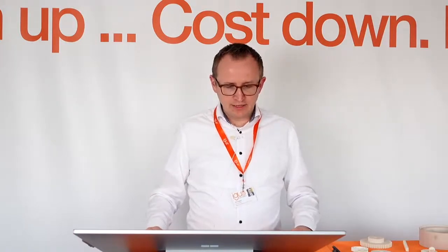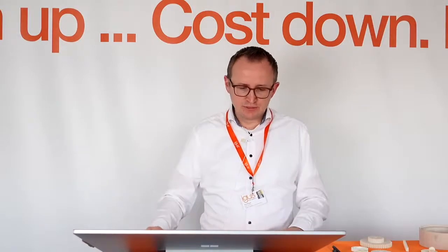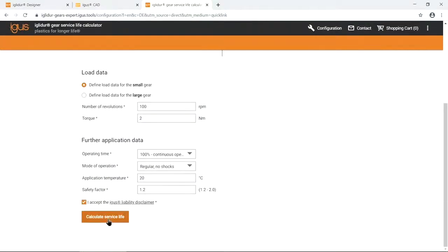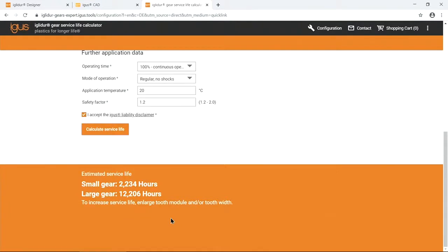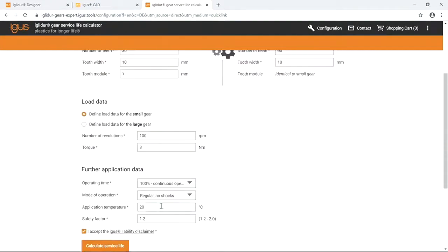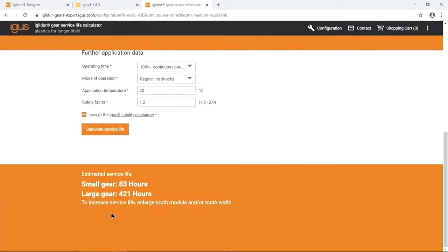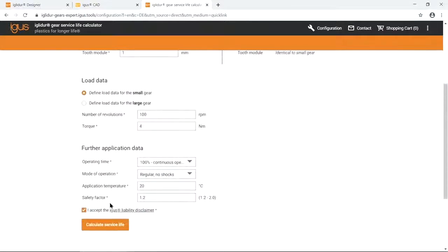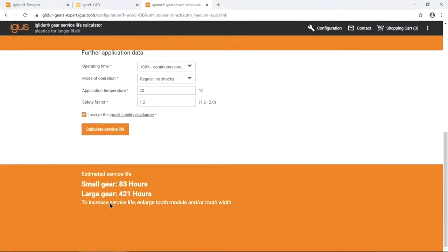But let's say we now have a stronger application. I'm increasing the torque from 1 to 2 Newton meters, and no change so far. I'm explaining later why. Okay, so at 3 Newton meters, we see already a big change here. The lifetime is a lot reduced, and if I'm increasing to 4 Newton meters, you see it's a really low lifetime in hours in this case. And yeah, let's say you have such a case, then it's not done by saying, okay, it's not working, I can look into something else, because now it's the point where you can play with the gear lifetime calculator, how you need to change the gear so that it holds for your application.